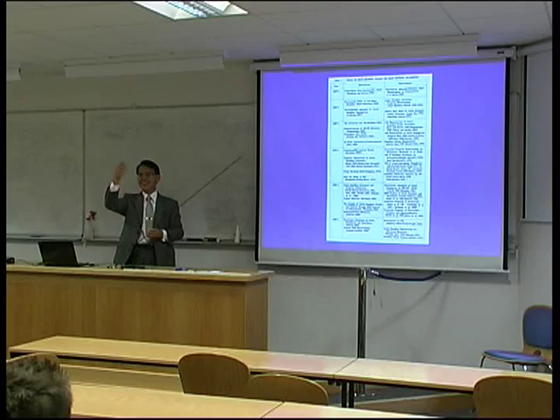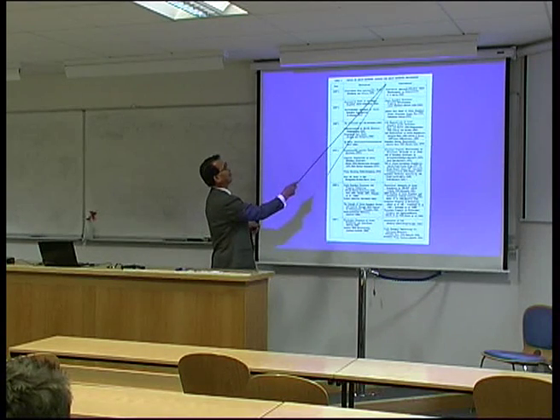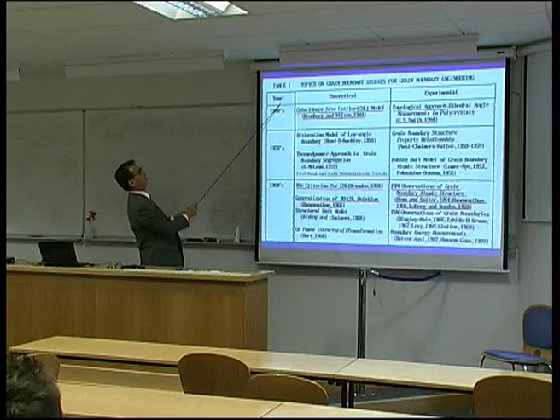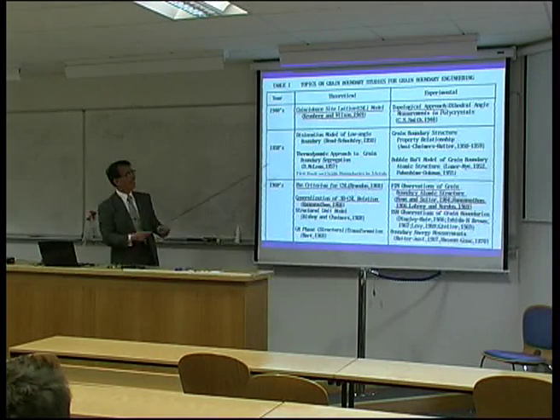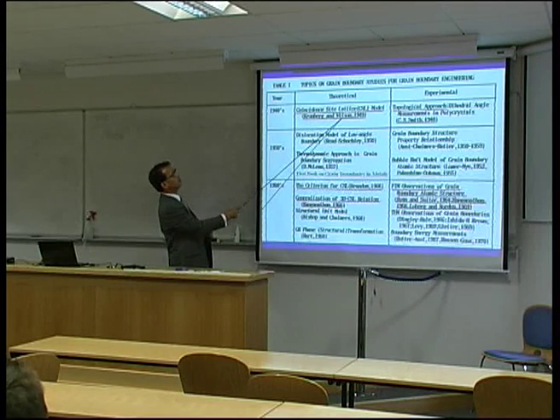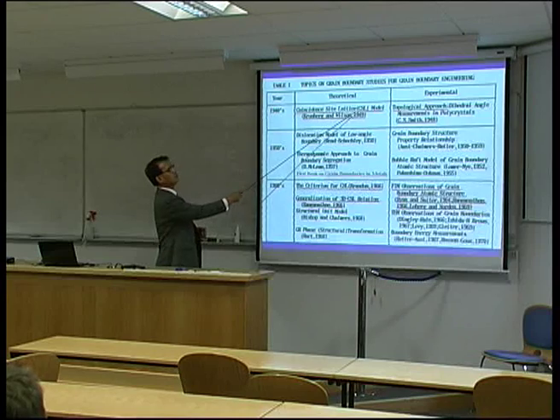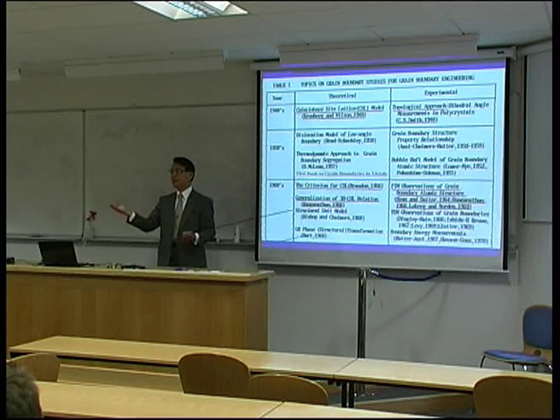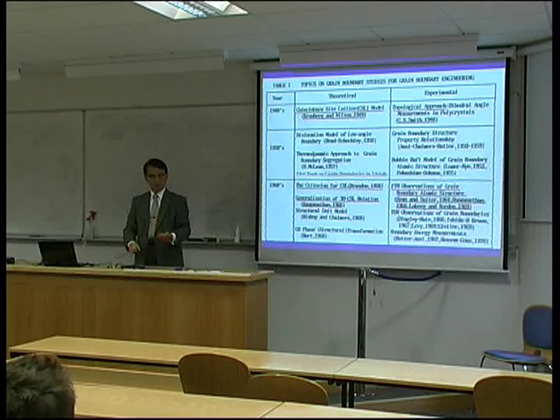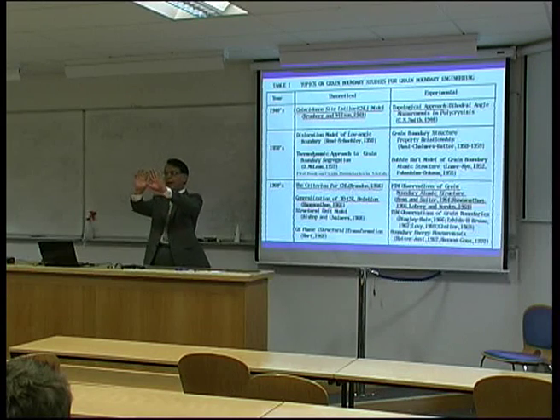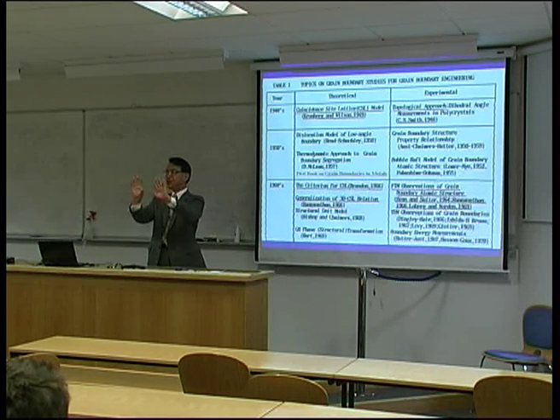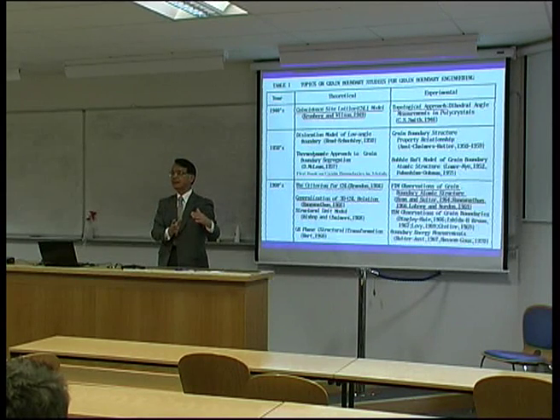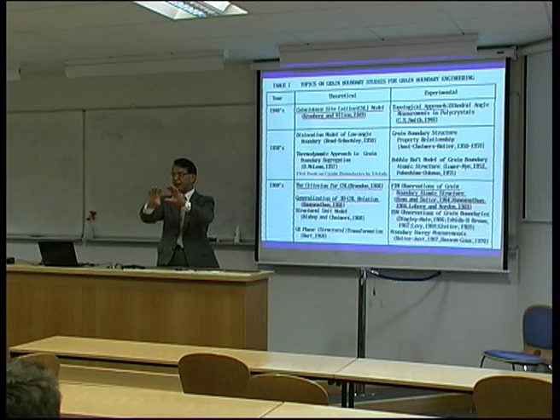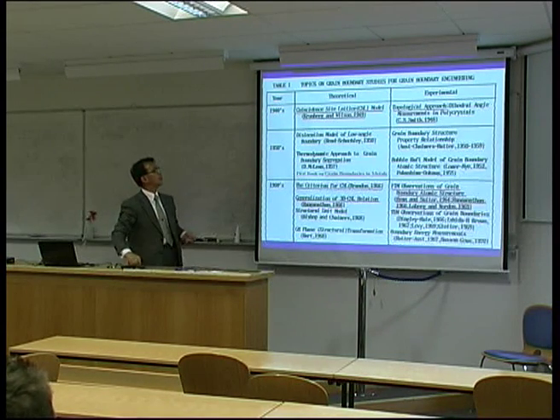And then, if we summarize the brief history of the progress of the study of the grain boundary, theoretically and experimentally, if I close up from 1940 to 1990, Kronberg and Wilson proposed the coincidence site lattice model, which we briefly call the CSL model of grain boundary. This is a more general model. Depending on the misorientation angle, at a specific misorientation angle, we can get a super lattice. So at the boundary, we can expect a rather ordered structure, not a random structure. This is very basic.